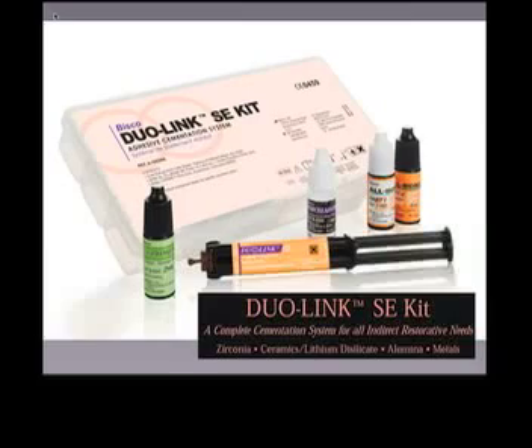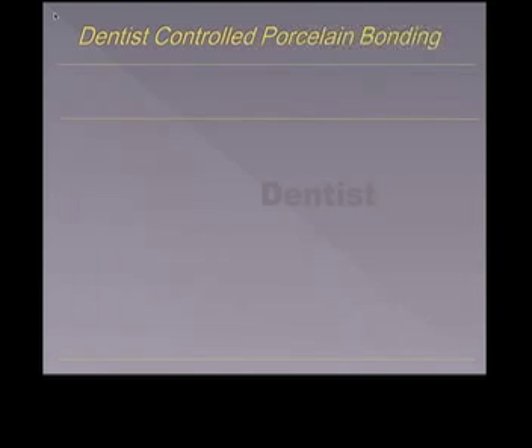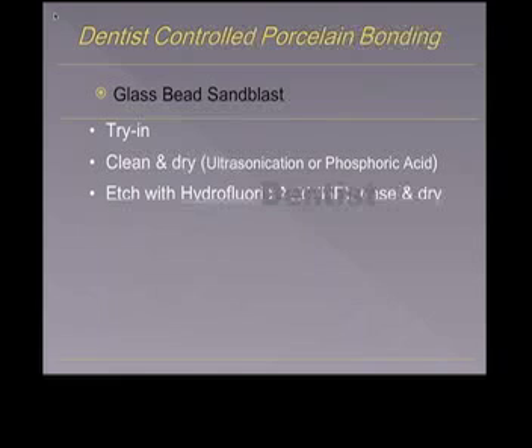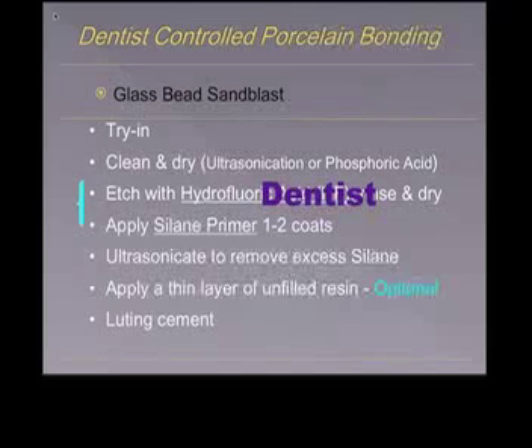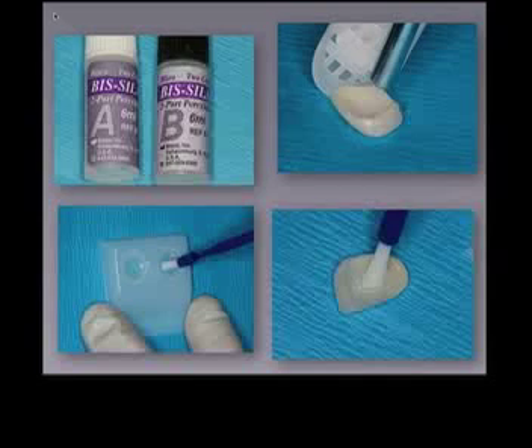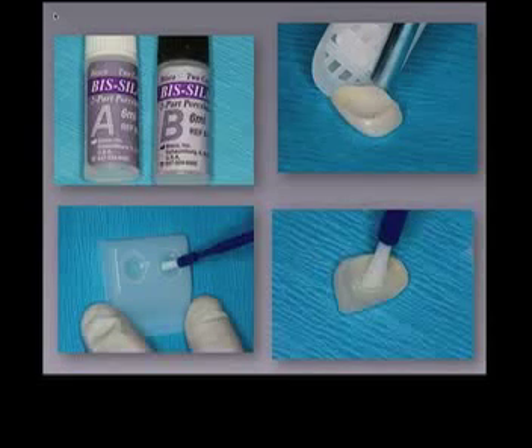BISCO introduced 9.5% hydrofluoric acid to reduce the etching time from 5 to 6 minutes down to 90 seconds. Again, sandblasting with spherical glass powder is recommended, and this is the technique and protocol that we use. Silane is applied as soon as the restoration is received from the laboratory. Proper silane application is 1 to 2 coats, allowed to dry for 30 seconds for the ethanol to evaporate, allowing the material to flow into the hydrophilic ceramic surface.